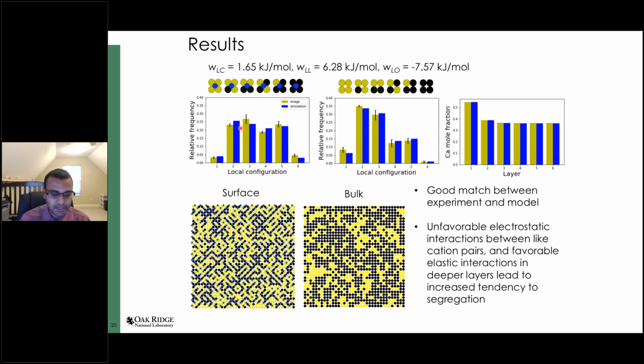So remember I said that there are 3 different components to the loss. So these are the 3 different histograms that we get based on the image and based on the simulation. And you can see clearly that by incorporating this XPS data, right, so we can clearly model the XPS data, and it really helps us because although we can't see the atoms underneath the surface, we can at least get some microscopic statistics of what's going on layer by layer, and we can use this to constrain the model further. And then I can take this model, and then I can start to do things like I can look at what the bulk looks like in this model according to what the optimized model says.